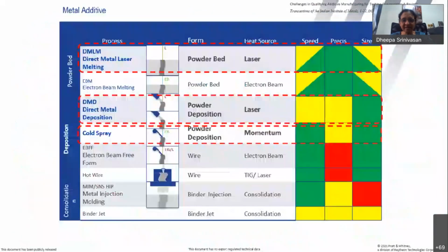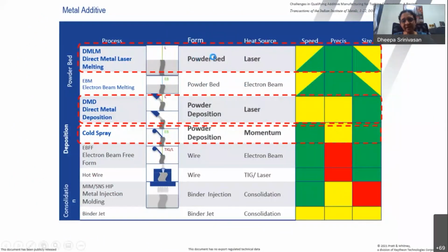Remember, I shared this slide with you. So, for example, laser powder bed fusion. The lasers are typically 1 kilowatt. Now you get up to 1 kilowatt. Typical lasers are 300 to 400 watts. And this entire thing has to be done in an inert atmosphere. There is a build chamber, and inside that, it has to be argon, sometimes nitrogen. You need to have an inert atmosphere because otherwise there will be oxidation of the metal powder.